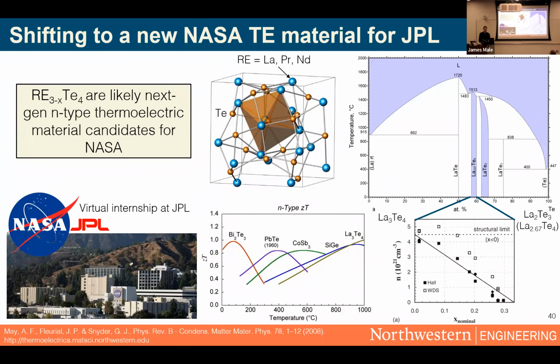So in this project, we investigated rare earth telluride thermoelectric materials. These are really promising next generation thermoelectric materials that typically have lanthanum, praseodymium, or neodymium as a rare earth element. And lanthanum telluride is kind of the best studied of the three. And you can see that its ZT is incredibly high at very high temperatures. So this could potentially give you great performance for really deep space, high temperature space applications.